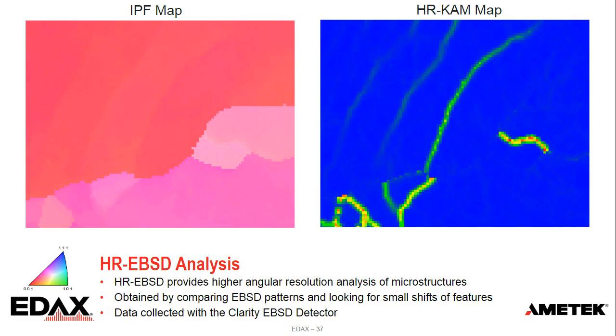And we can look at this with what we call HR, high angular resolution EBSD. This is a technique that provides higher precision in the orientation data. This is achieved by comparing two EBSD patterns in a cross-correlation Fourier space, looking for small shifts of features within the pattern. This is in contrast to our standard Hough-based indexing. This is data that was collected with our Clarity direct detector to get really high quality patterns, looking to see how well we could measure this. From this, you can see the orientation map. There are some slight color changes in this top grain as far as variations. And when we do this HR KAM map, you can see how we start to very clearly resolve where some of those cell walls are present.